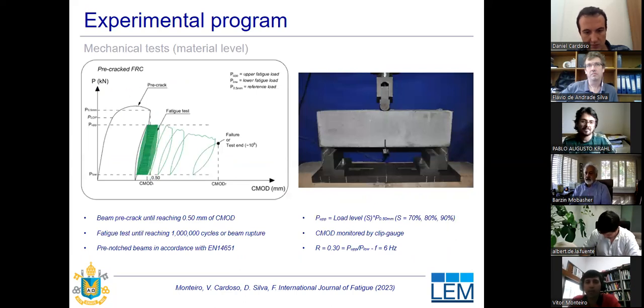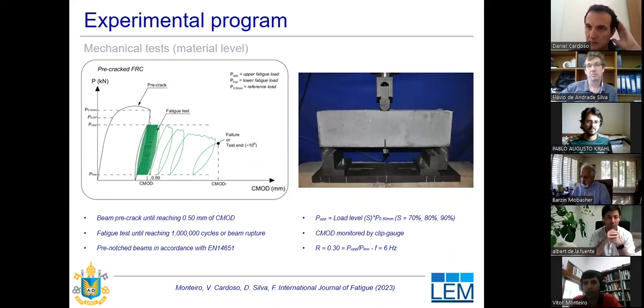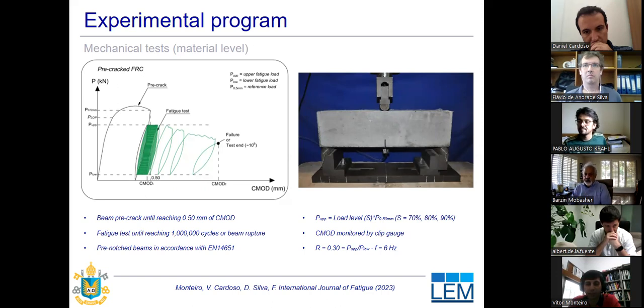The experimental program to evaluate the mechanical degradation in the material level consisted of pre-cracking the pre-notched beams until reaching a CMOD, the crack opening, of 0.50 millimeters. The beam was unloaded, and then the fatigue test began. The fatigue test consisted of oscillating the loads between the upper load and the lower load, while the upper load was a percentage of the flexural residual strength, 70%, 80%, or 90% of the recorded load from the pre-crack at 0.50 millimeters of CMOD. Along the fatigue test, the CMOD was monitored, recorded by the clip gauge, and the fatigue tests were carried on until reaching 1 million cycles or rupture.